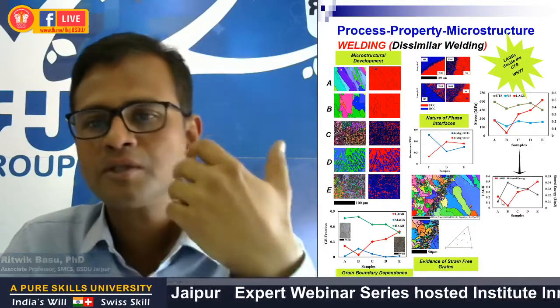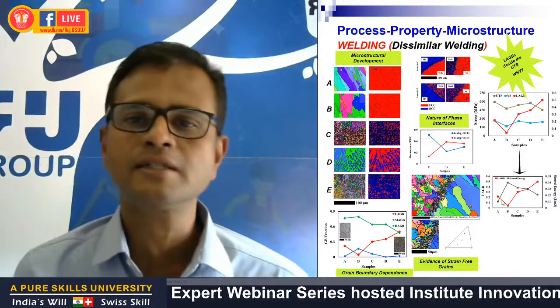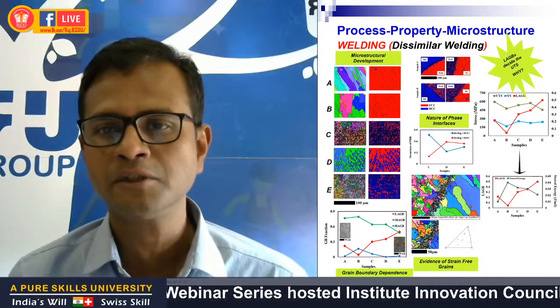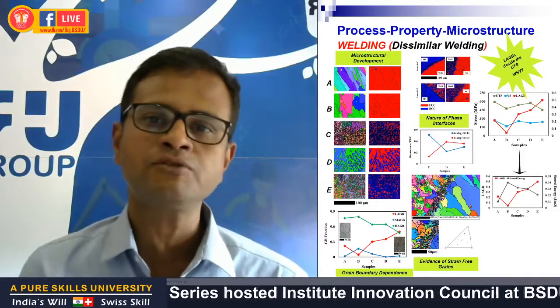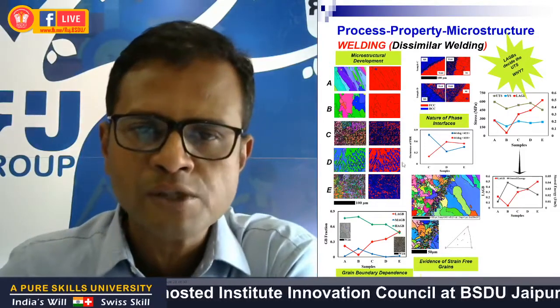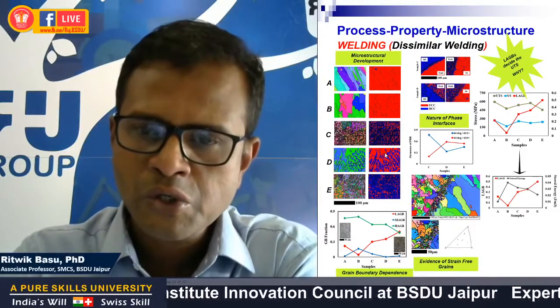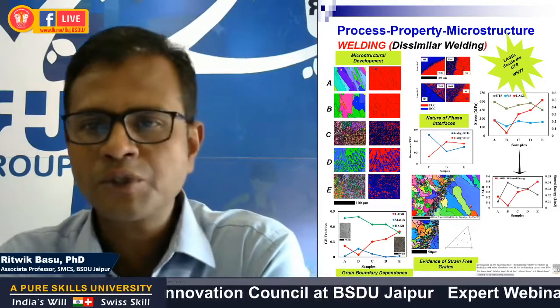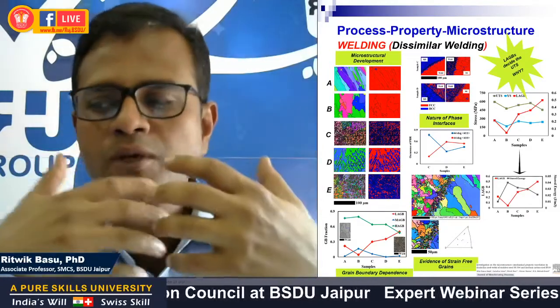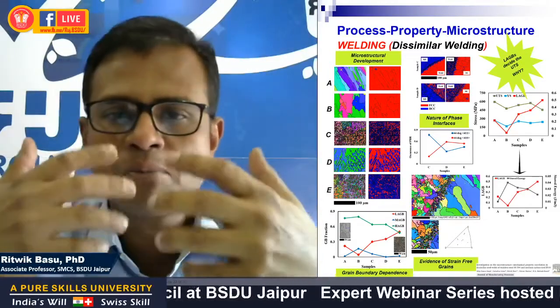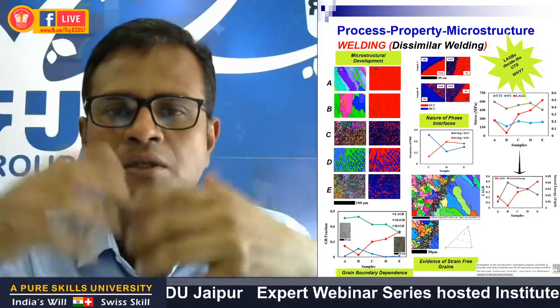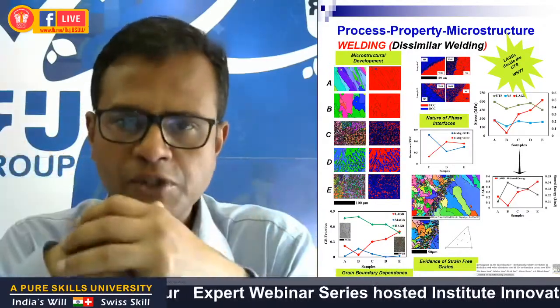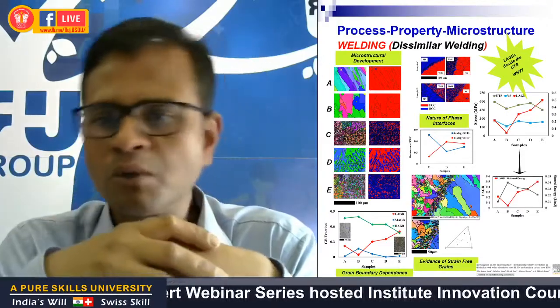And we have also seen that with increase in the ferrite content, the impact energy in the samples reduced, especially for the samples that exhibited a two-phase microstructure. So overall, we have shown that a two-phase microstructure is indeed important for imparting a good combination of strength and toughness. So this was a work of mine.